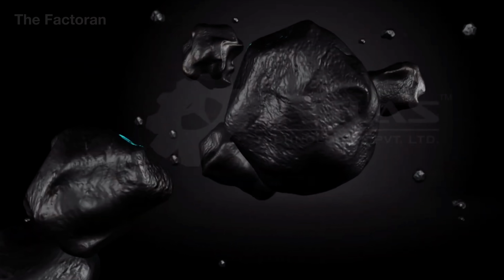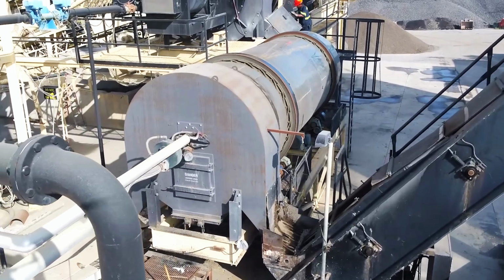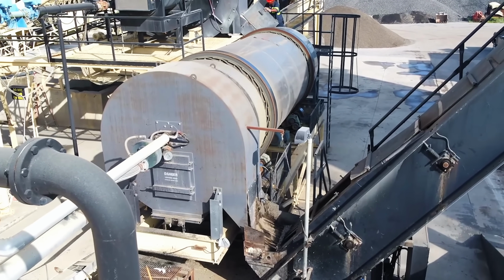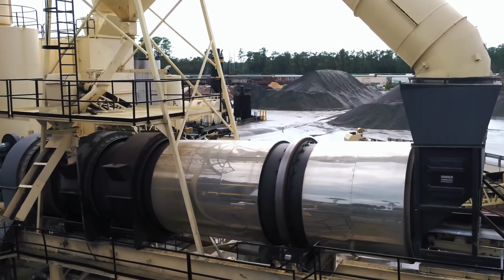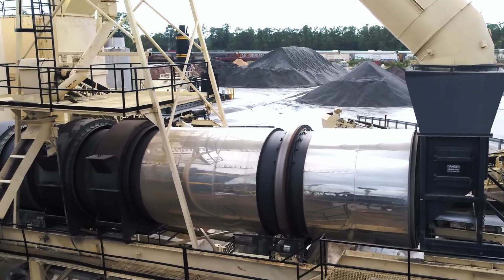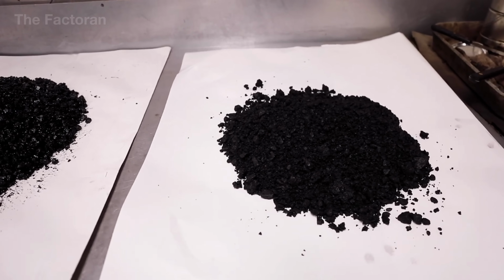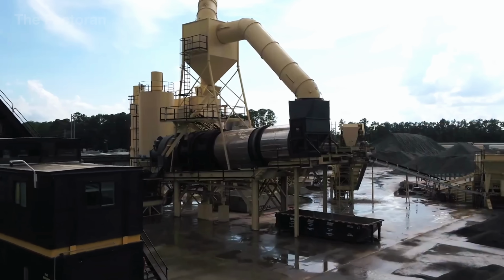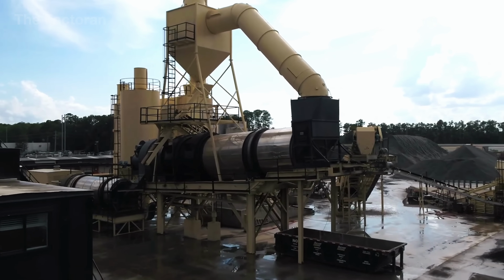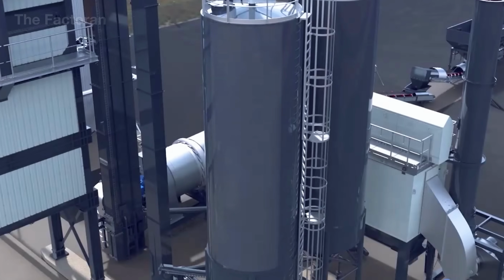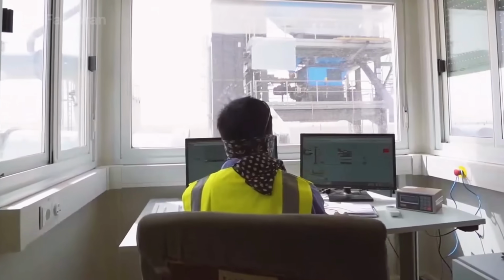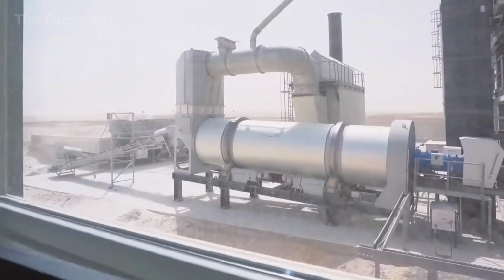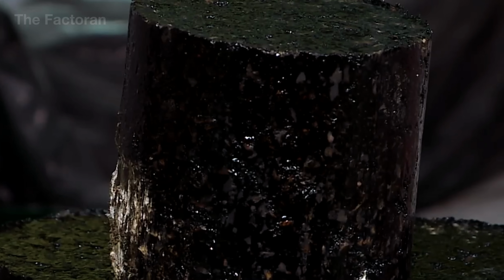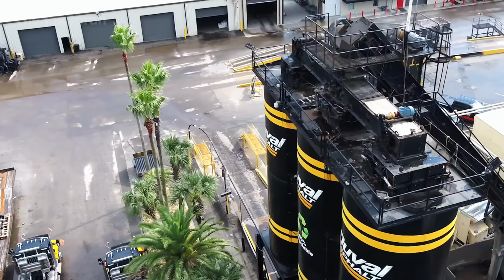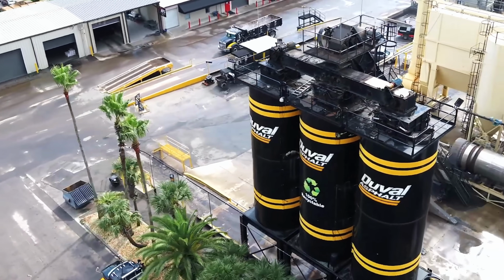All of this flows into the forced mixer, a sealed steel chamber with two massive counter-rotating shafts. Their motion blends the materials thoroughly, coating every grain of aggregate with hot binder and filling every gap. A mixing cycle lasts about 30 to 45 seconds, with temperature carefully maintained so the blend is neither too stiff nor too runny. The entire process is closely monitored by a central computer system, from material ratios to mixing time, ensuring every batch achieves uniform quality.